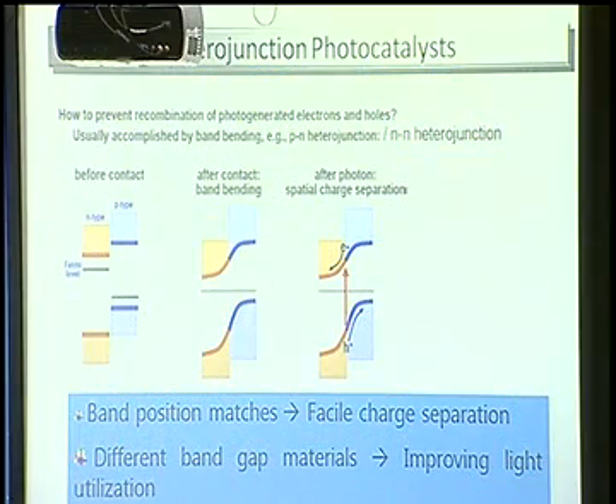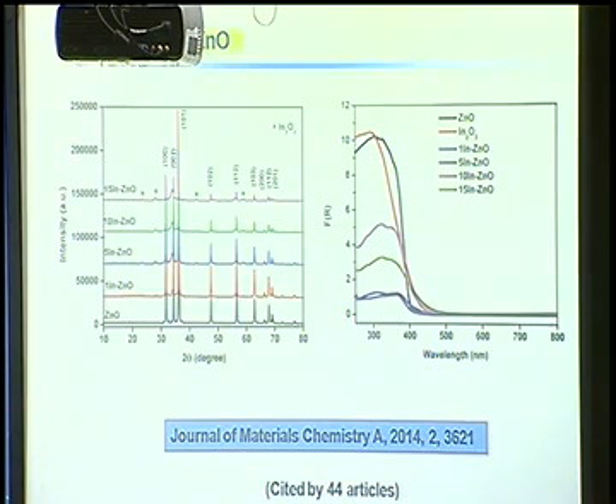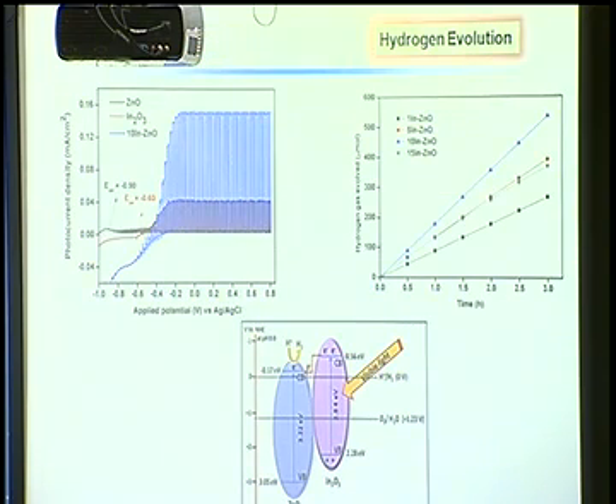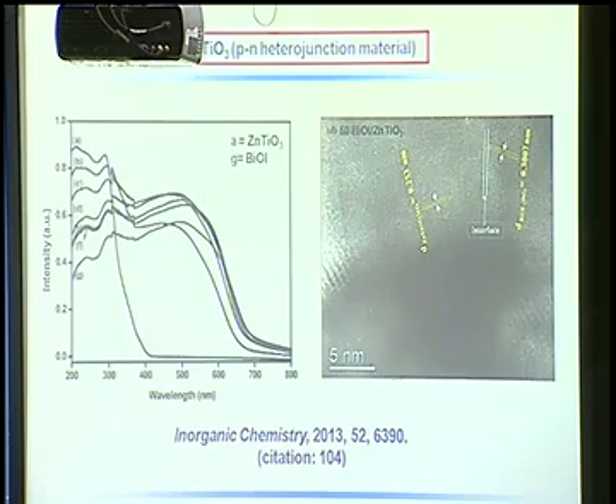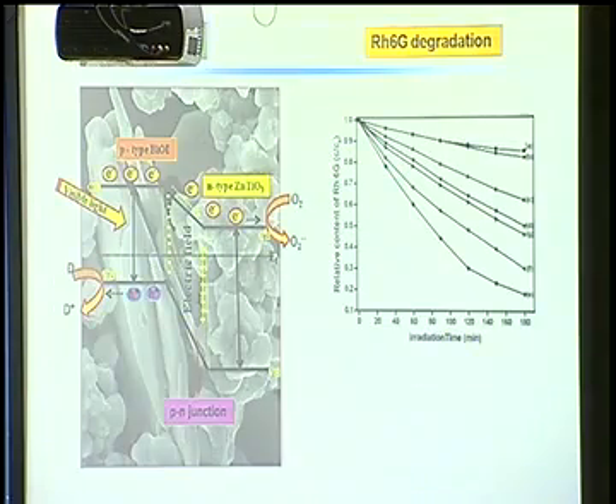The next question is how to increase the charge separation efficiency. By giving importance to heterojunction photocatalysts, we can improve the charge separation efficiency. In this regard, I have developed a material in which I modified zinc oxide with indium oxide, and this material is reported in the Journal of Materials Chemistry. It also gives very good hydrogen evolution under visible light irradiation. This is also another material, and this paper has been published in Inorganic Chemistry.